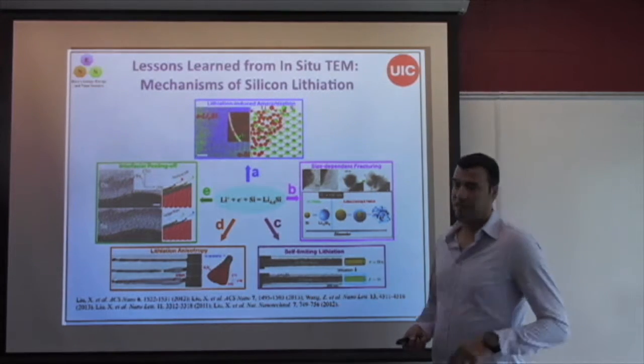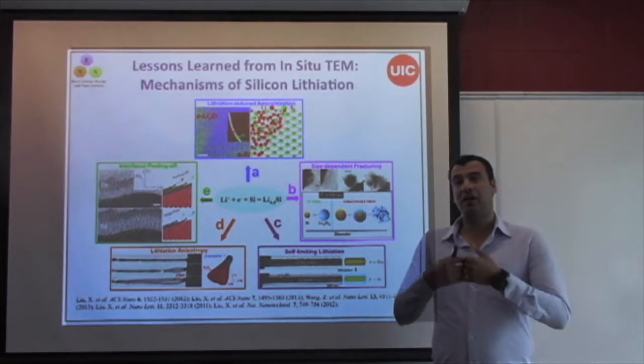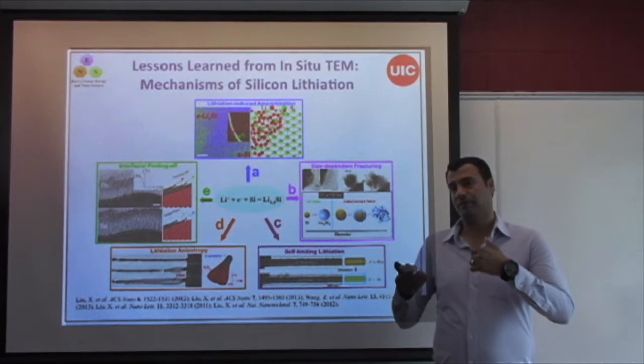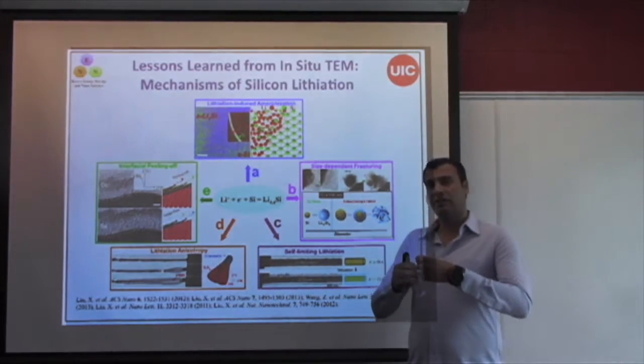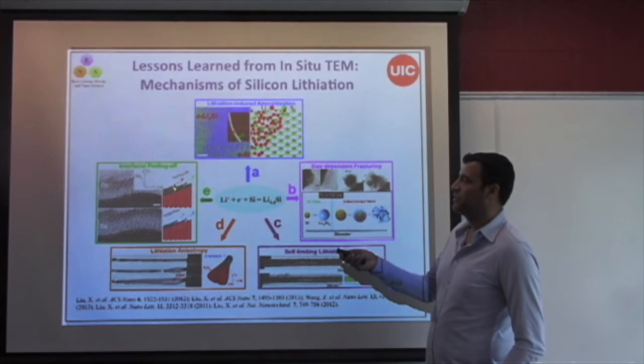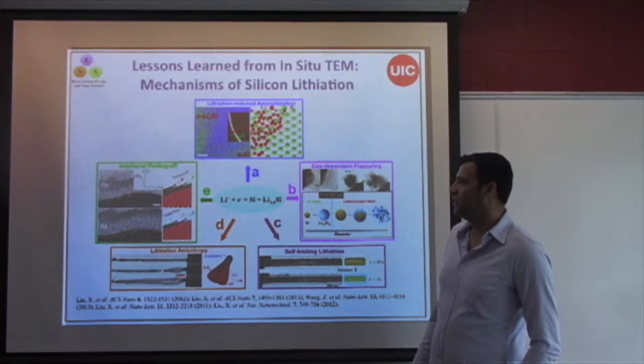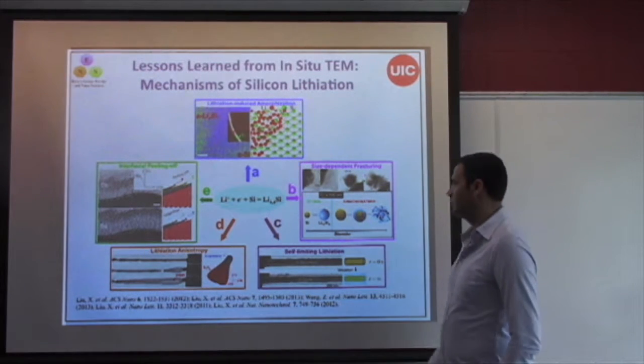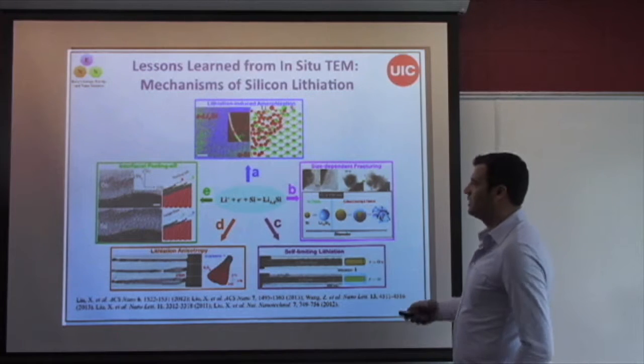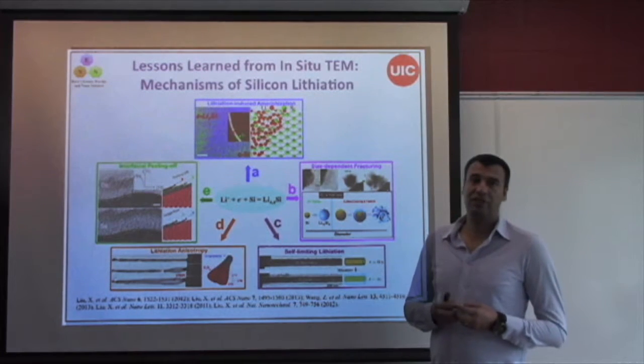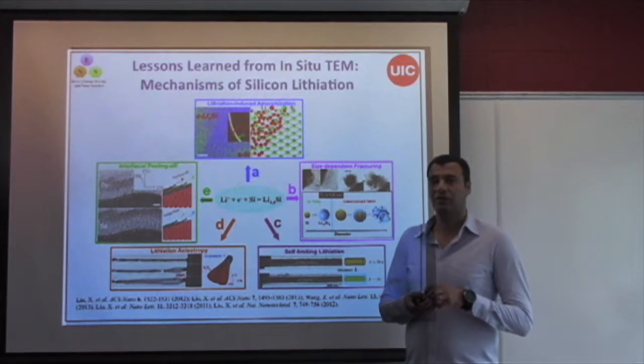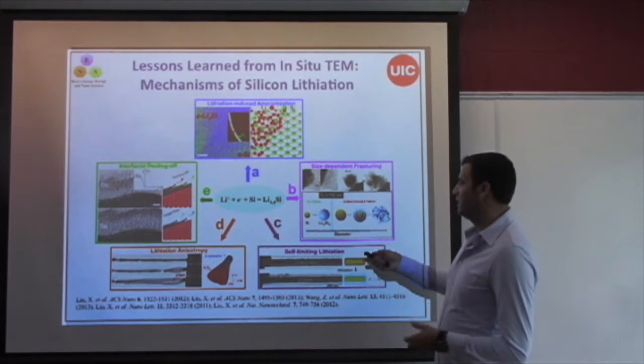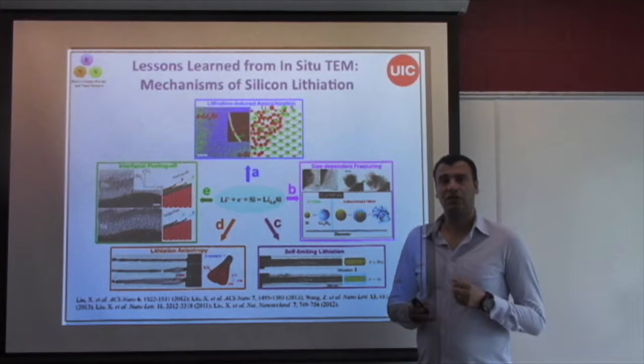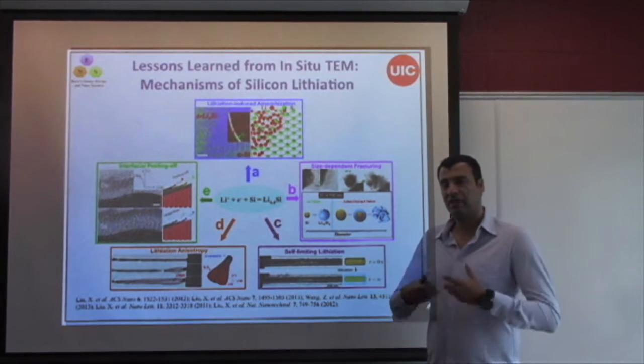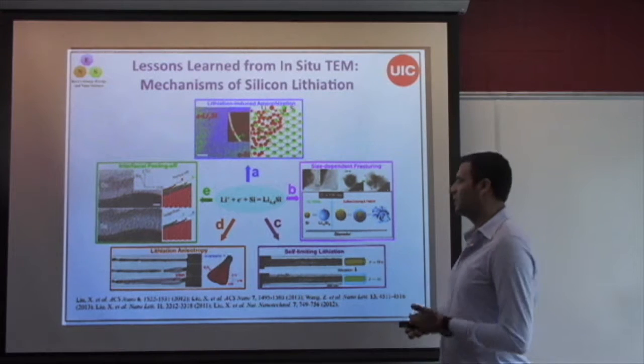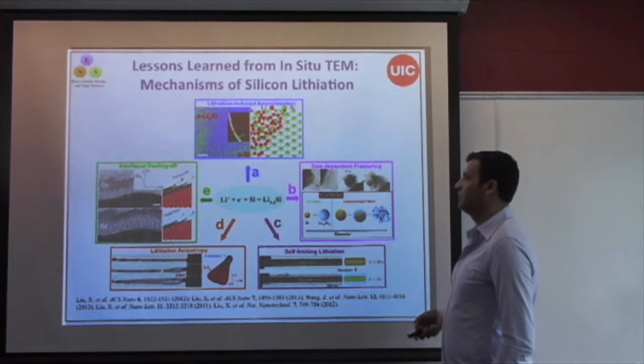Another interesting work looked at the interface between amorphous and solid phases, and how crystalline material will transform to an amorphous phase. This work showed a peeling mechanism at that interface. Another interesting work looked at fracture and failure of electrodes of various sizes, and was able to draw a better conclusion about the safe range for the size of electrode particles that we can apply in order to avoid fracture of the systems.